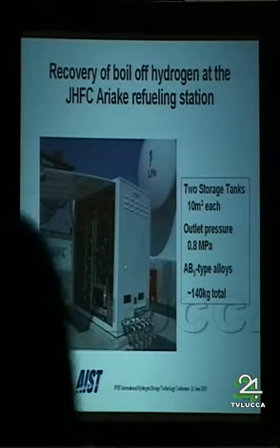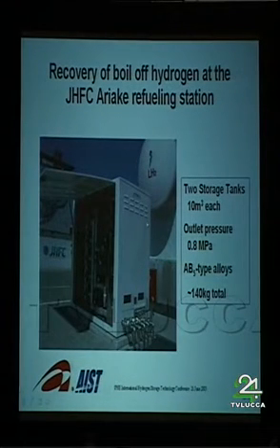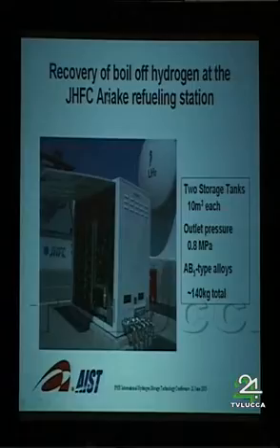And this is a detailed photograph of recovery of boil-off hydrogen using metal hydride. There are 2 storage tanks. The capacity is 10 cubic meters each, and the outlet pressure is 0.8 megapascal. They use AB5 type alloys. In total, 140 kilograms of AB5 type alloy was used.